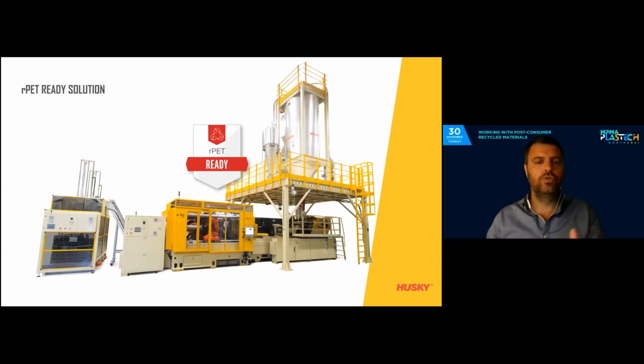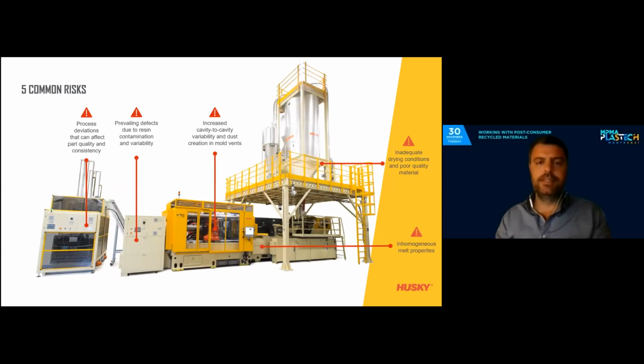So the rPET solution technology, our HyPET5e, is our standard solution with an integrated PET preform solution from pellet to preform. So we have the dryer, the resin preparation, the melt preparation, and the molding and conditioning of the preform, all in one system, fully integrated and controlled. Also with our extended experience in PET processing. So as I said, the system is the best foot forward to handle rPET, but we cannot talk about one rPET.